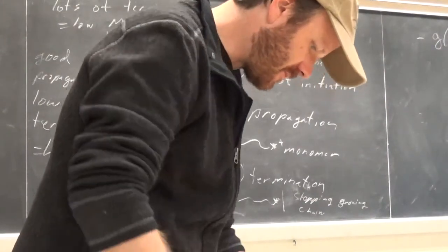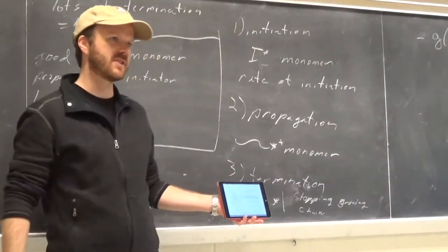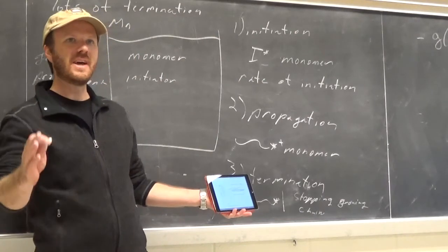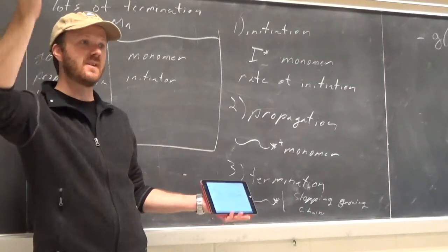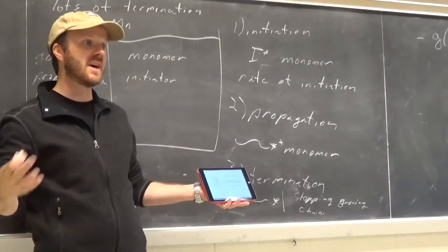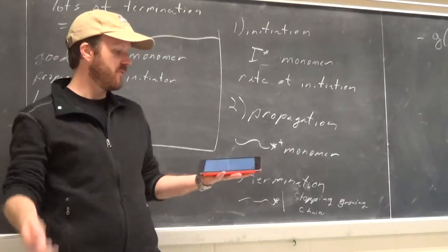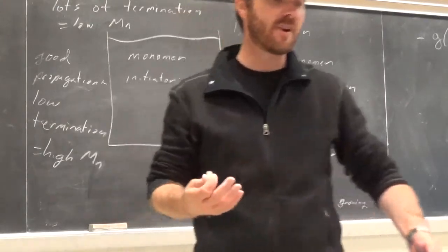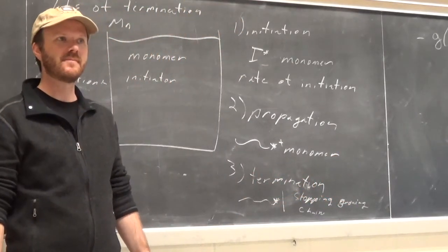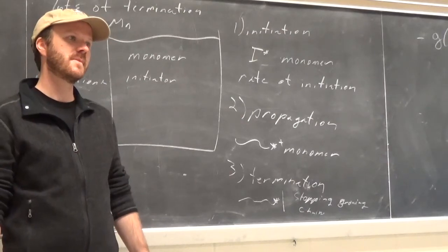So if you look at notes 9 on slide 15, you see crystallization as a function of crystallization time, right? If you let the polymer sit between TG and TM, the crystallinity will increase as a function of time because you're giving the chains more time to crystallize. If you quench a polymer and don't give it much time to crystallize, it's going to be amorphous. You'll get X-ray patterns and DSC patterns indicative of an amorphous polymer without any crystals in it. Would quenching increase the orientation?